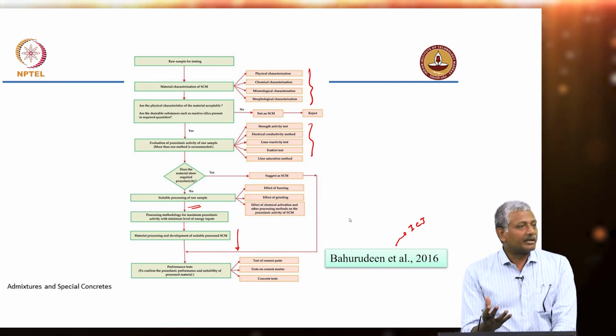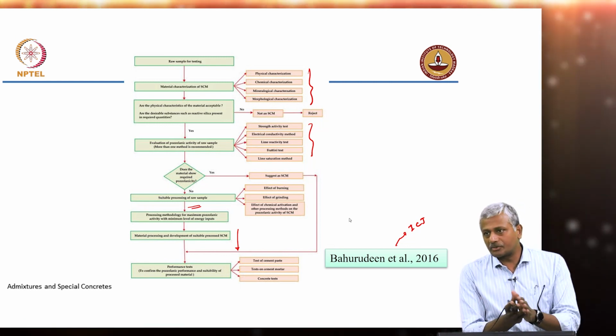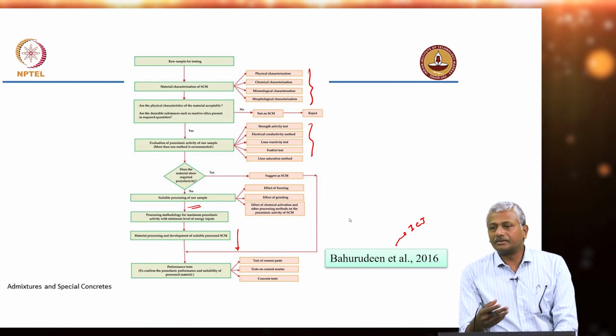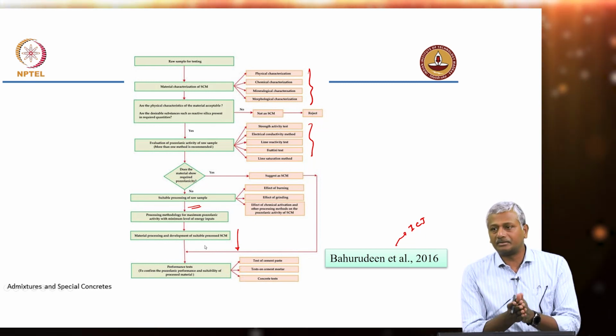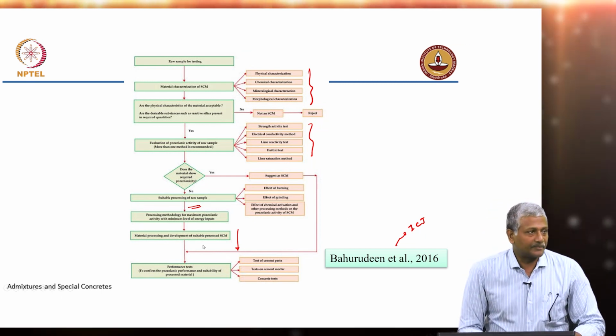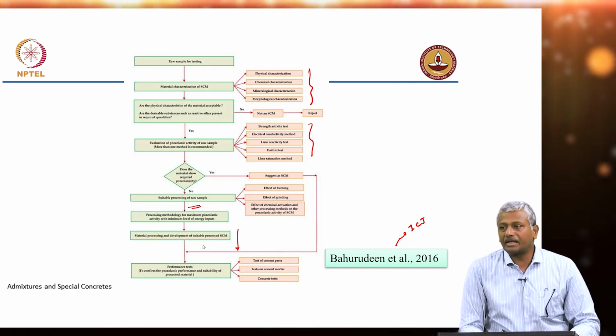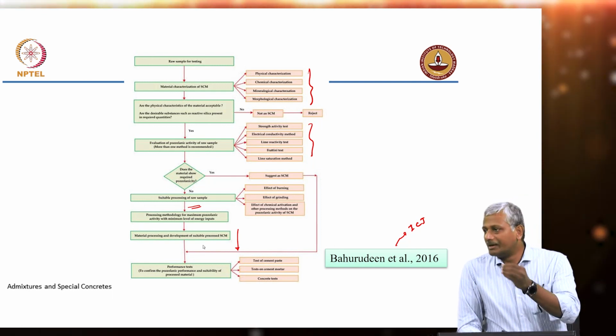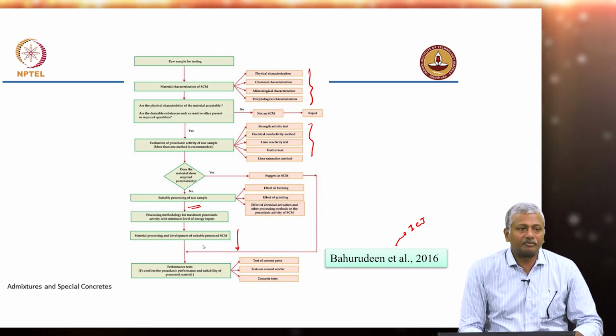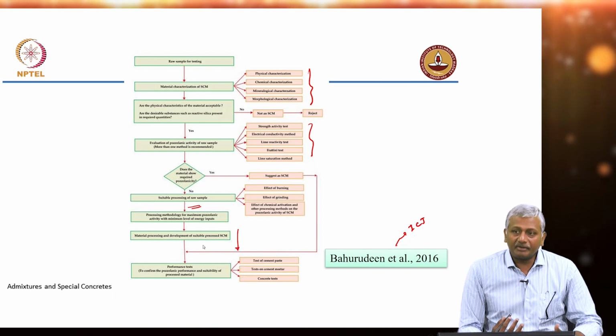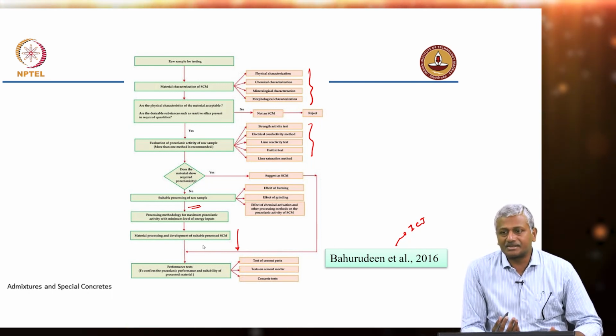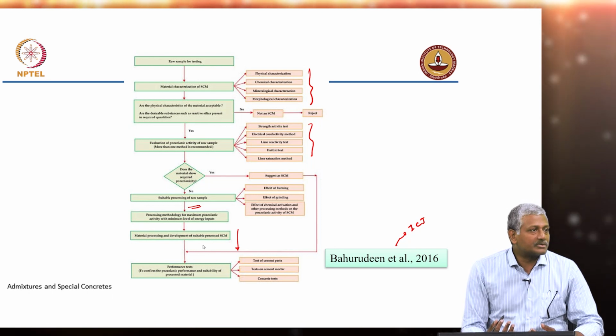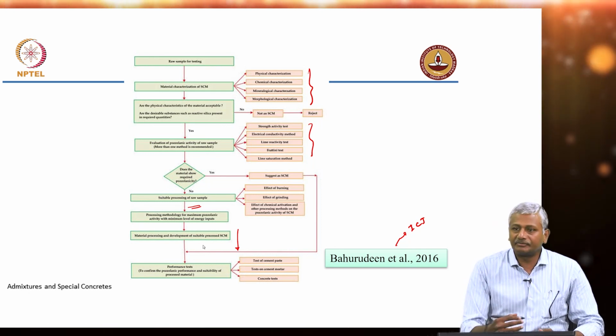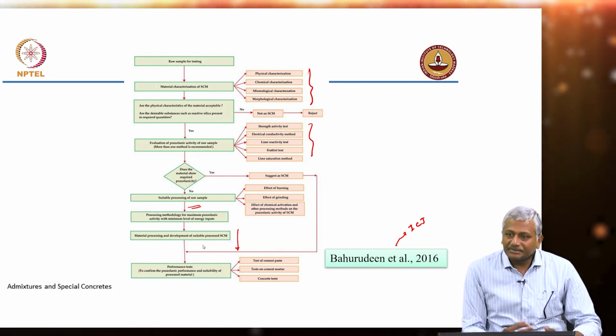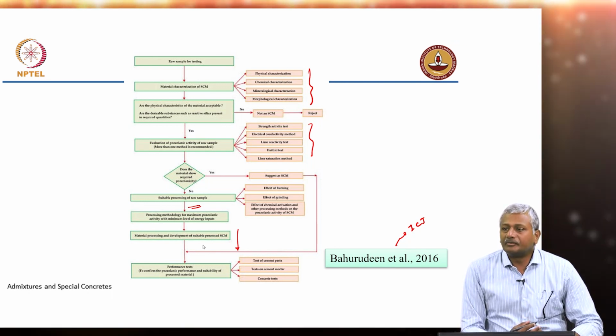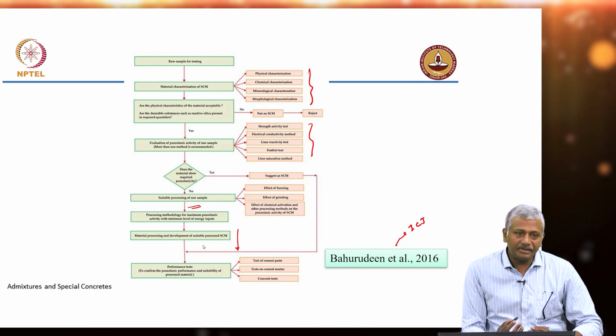When you have calcined clay as a supplementary cementing material, because of the structure of the calcined clay itself, we saw earlier that your PCE molecules get intercalated. They go between the layers of the calcined clay, and that can lead to incompatibility when calcined clays are used. So you have to probably dose a higher amount of chemical admixture to get the same level of performance. So all of these aspects you need to be aware of, because compatibility is complex as it is. When you are actually complicating the cementitious material composition even more by adding further ingredients, you can imagine that this scenario is going to get further worsened if you don't address it early enough.